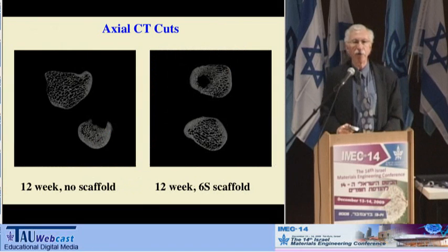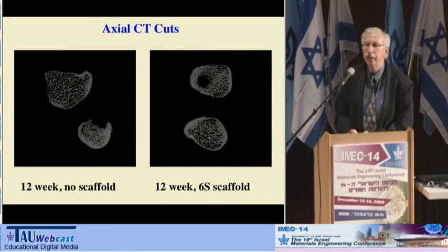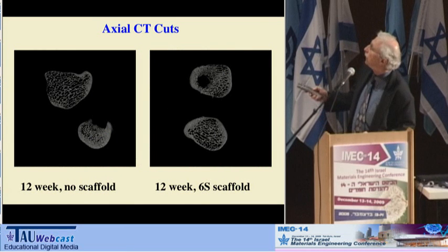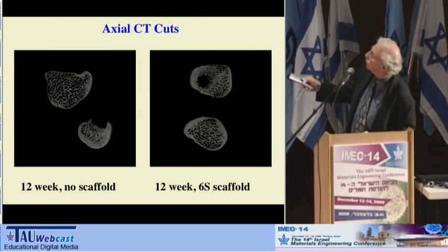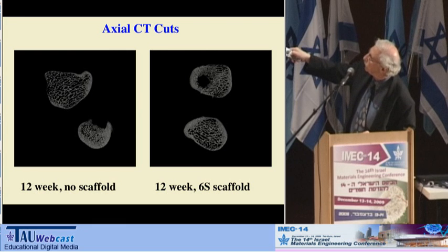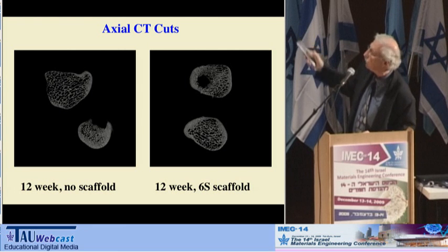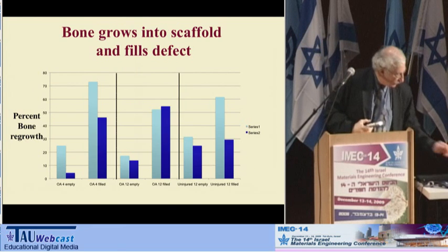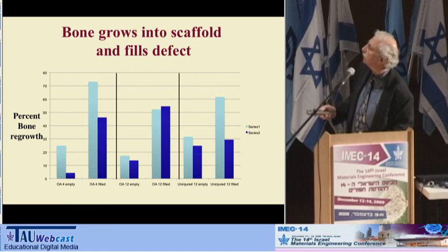We used the micro-CT method to examine the mineralization. And here's the cut in the control. Here's the cut where the scaffold was put in. Unfortunately, this is the contralateral side, the control, and they kind of got reversed. So this one and this one are the two controls. Here's just the divot that was drilled with no scaffold. Here's with the scaffold. And if you examine the data here, this is % bone regrowth.